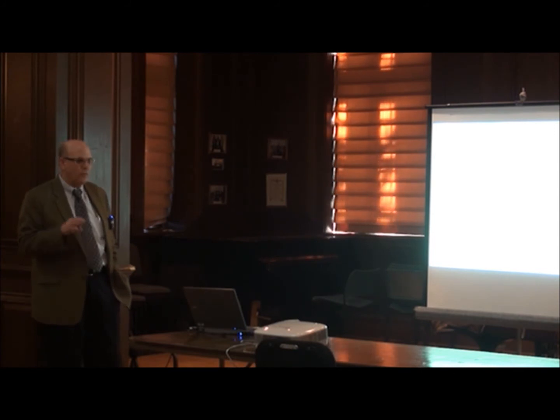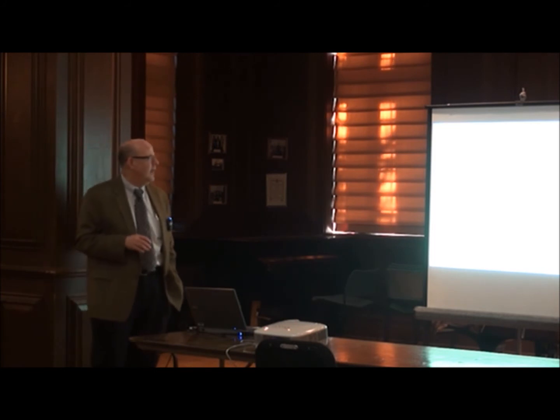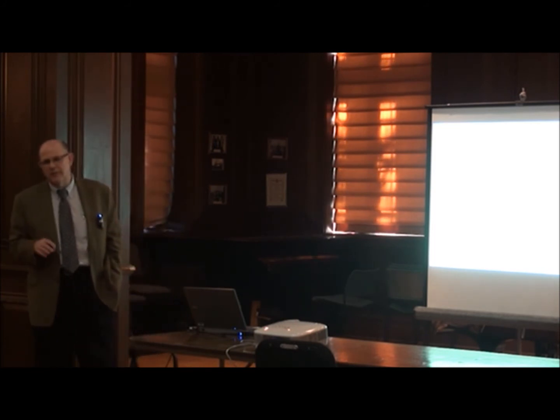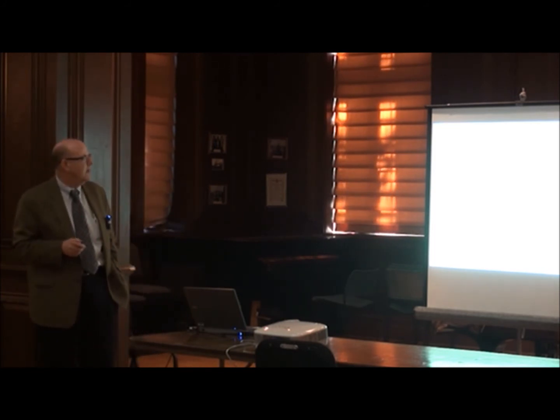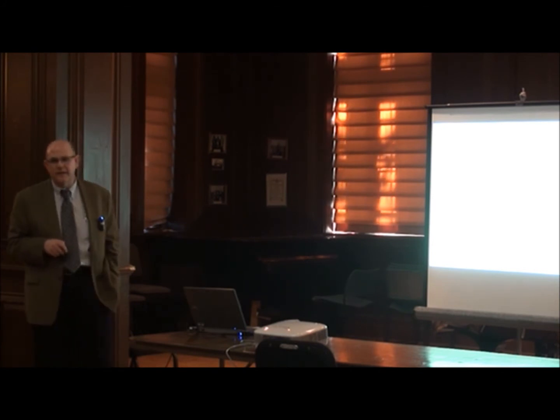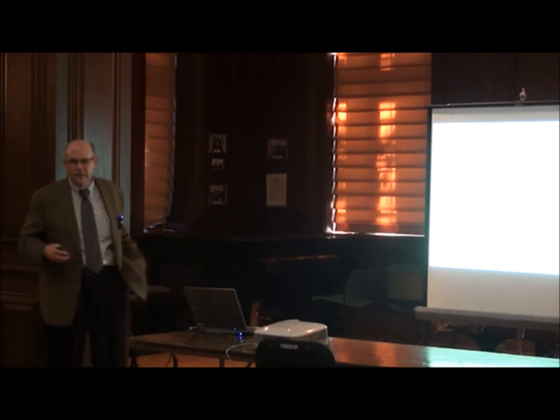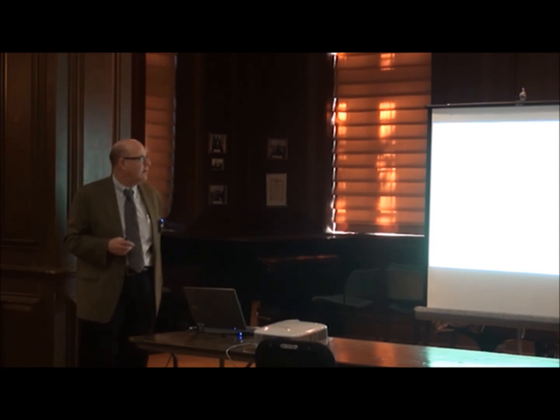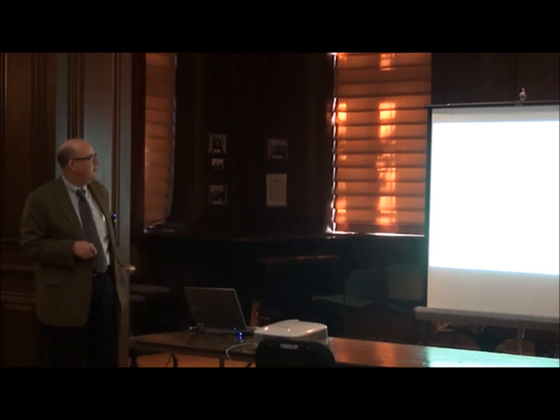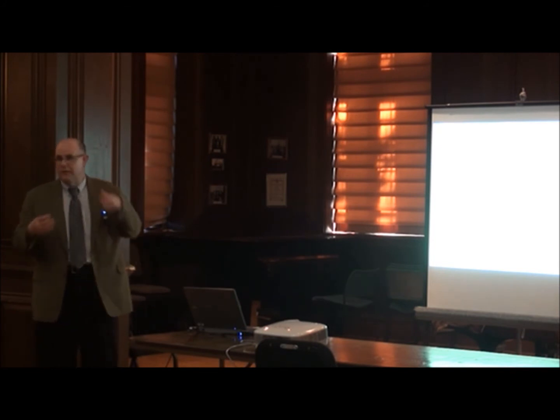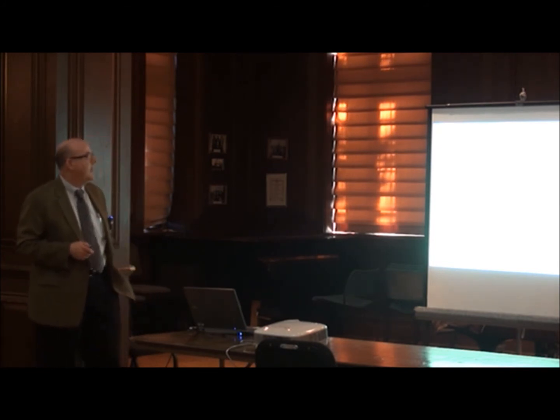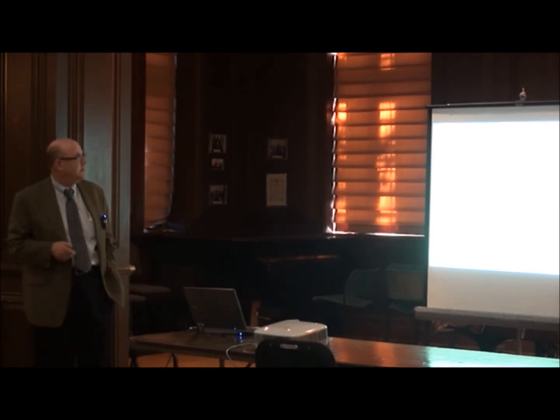And that's called, for certain systems, an elasto-hydrodynamic situation. That's a whole other topic we won't have time for. But the idea is that they physically aren't touching across the interface, but they're close enough that even under those conditions, we are getting elastic deformation of the asperities from the opposing asperities through the fluid. And that causes an effect on friction and so forth.